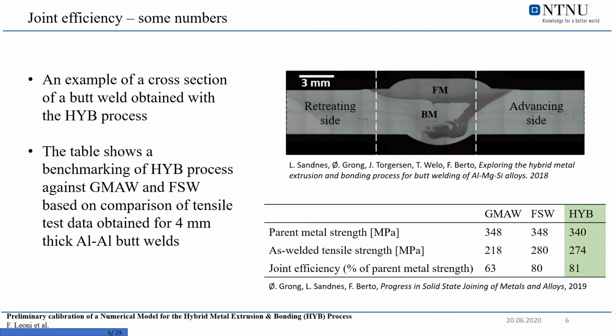In this slide, you can see an example of a cross-section of a butt weld obtained with the HYB process. As you can see, it can be recognized the filler material and the base material. This is an aluminum butt weld, so you can see how the filler material is mixed in the groove, and this is made by the rotation of the pin, which passes through along the welding direction and rotates. So it's similar to the principle of friction stir welding, but here we have a gap between the plates, which is filled by the filler material.